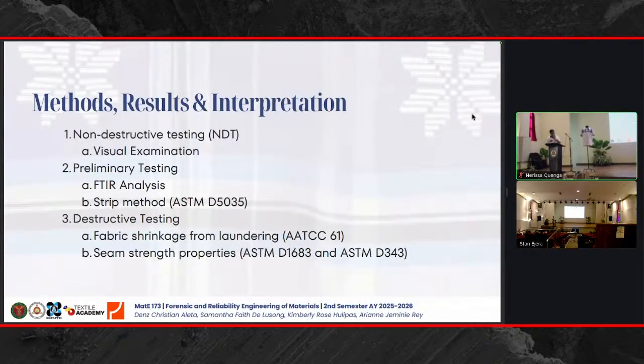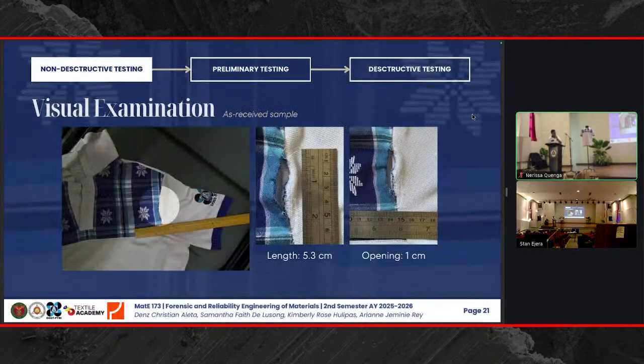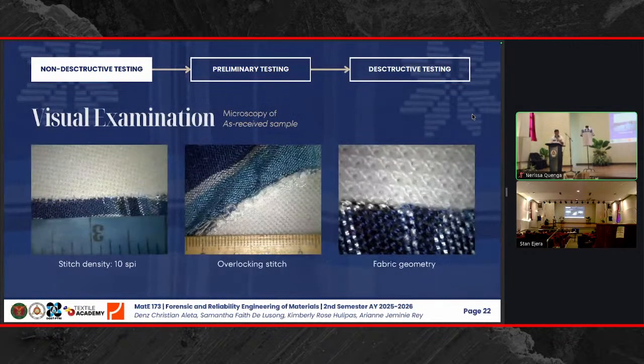For the methodology, a visual inspection was first conducted as a non-destructive test to assess the severity of the failure. Preliminary testing was then performed on the raw fabrics for characterization and supporting data purposes. Finally, several destructive tests were conducted on replicated samples to simulate the possible causes of failure. Now, the visual inspection allowed us to measure the seam opening length and the diameter of the front yoke attachment. Now, microscopy provided us the necessary data for sample replication and testing.